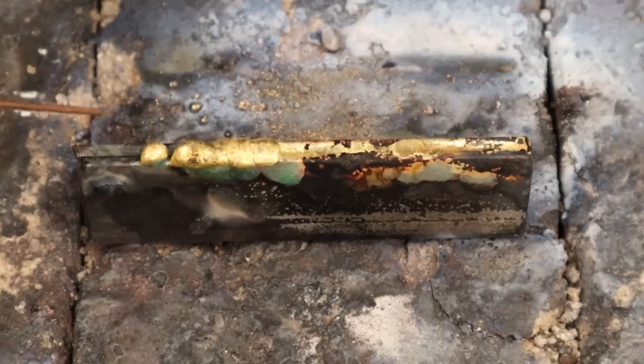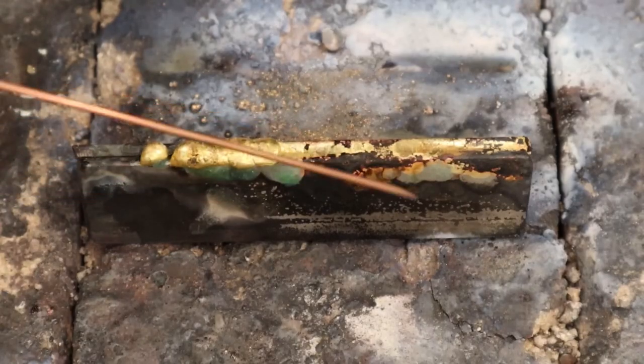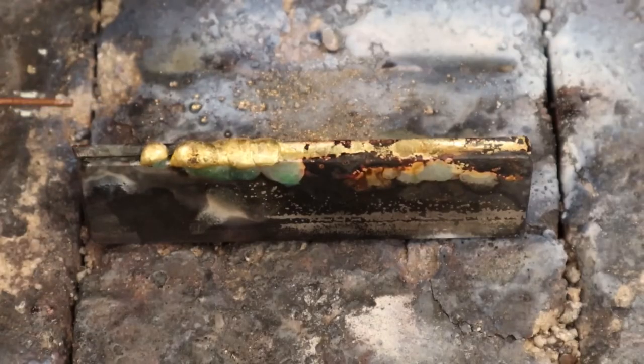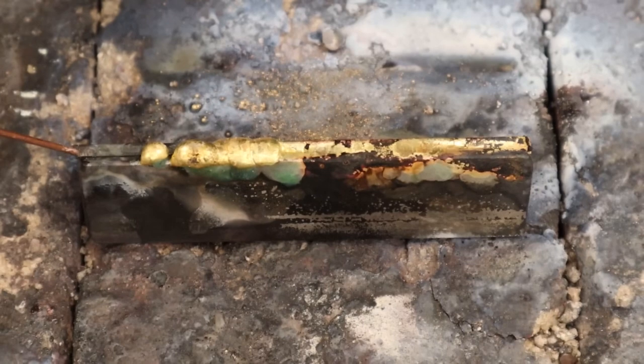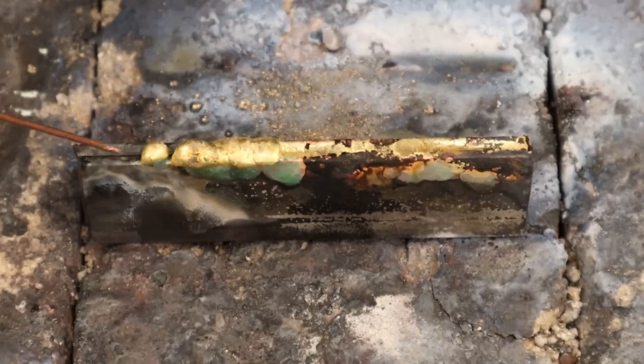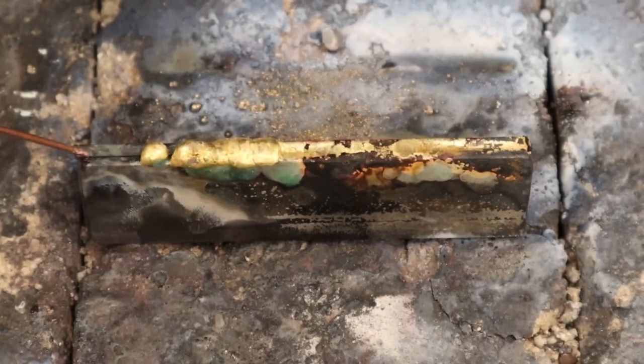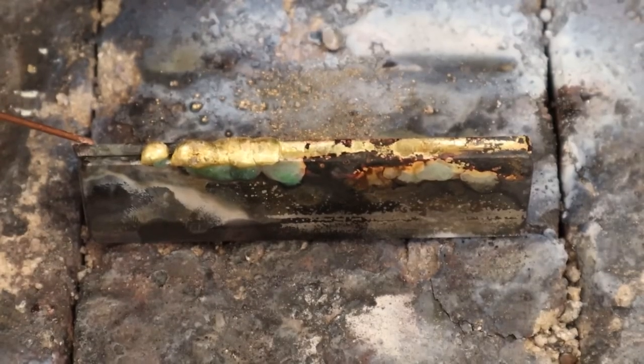All right, so take a look at this sample that we just did. Remember, this is the too cold side and this is the too hot. So I tried to make it as obvious as possible. Sometimes you have to exaggerate the scenarios to see it a little bit more clearly. Now, the side that I got cold on, I actually started right at the very corner. However, I was melting and looping the brazing rod right onto the top. So just from putting it in the water to chill the sample down, two or three of them actually just fell right off. So very little bonding to those surfaces.